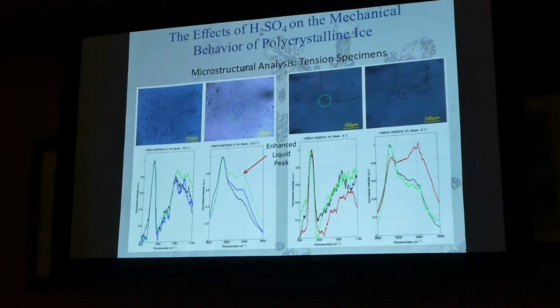So enhanced liquid peak. But in this sample, what we saw was sulfuric acid in these different places, which is shown by this peak here. And we saw 2 that were mostly ice with some liquid, but 1 that was just pure liquid, so right here. So for me, I spent many hours in the lab looking for this, and I was pretty happy to have finally found it a couple times.